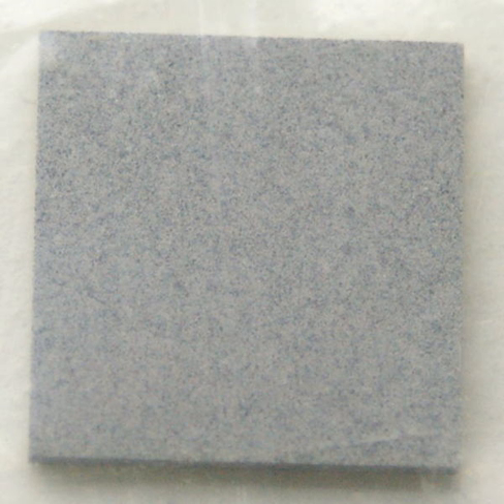Without an iron catalyst, the reaction is complete after several hours, approximately 7, when no further weight increase due to nitrogen absorption per gram of silicon is detected. In addition to Si3N4, several other silicon nitride phases with chemical formulas corresponding to varying degrees of nitridation or Si oxidation state have been reported in the literature.